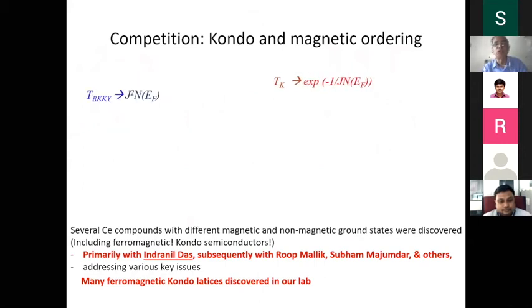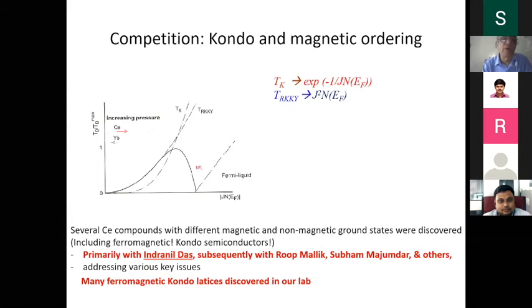One interaction is trying to increase magnetic ordering, which goes like this. The magnetic ordering temperature is going up like this. Another interaction is trying to kill magnetism. These two interactions compete, and the net result is that if you tune the interaction by applying pressure or by chemical doping or even changing magnetic field, beyond a certain critical point of the concentration or pressure, you will find that you lose this magnetism. It comes down at this point, and only this non-magnetic interaction dominates.